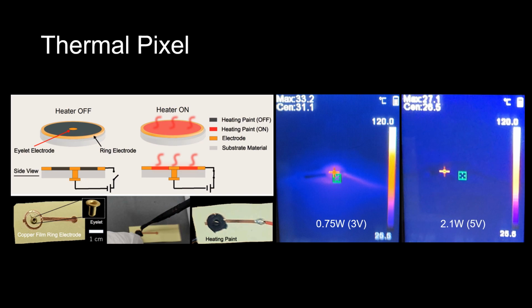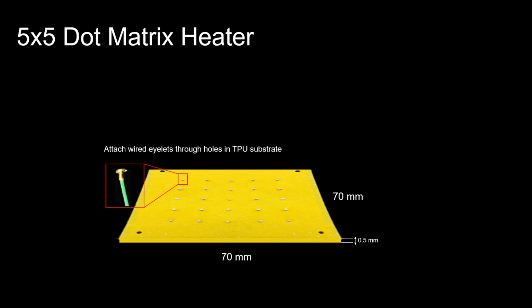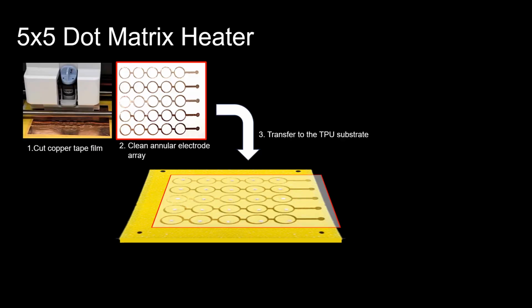Inspired by the via of the circuit board, we fabricated a compact thermal pixel using the metal eyelet and annularly cut copper tape in the form of concentric electrode. We then applied the heating paint to the circular space inside the outer electrode to create 1 cm diameter heater. We applied this method to create 5x5 dot matrix heater by attaching wired eyelet to the 3D printed TPU substrate.